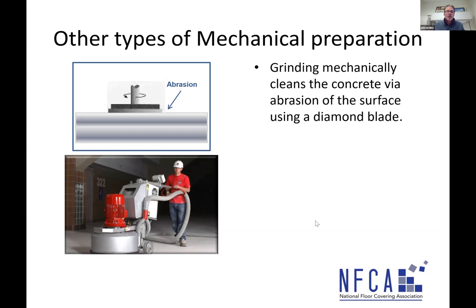I will say this though, you will have dust residue in the pores after grinding, no matter how good your grinder and vac system is. And you typically have to come back with a wand and do some deep vacuuming to get those minute dust particles out of the pores of the concrete that result from grinding.